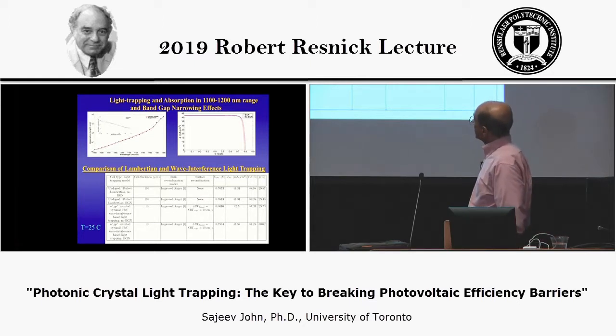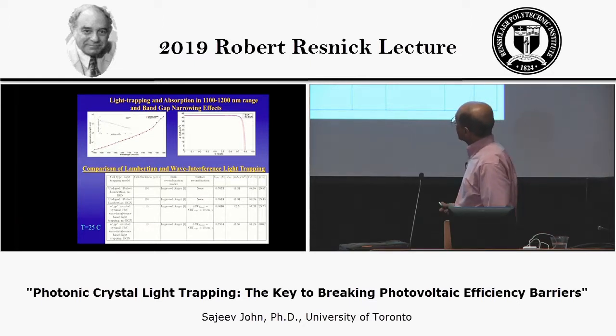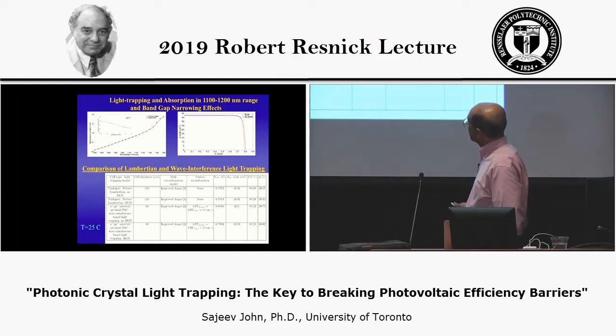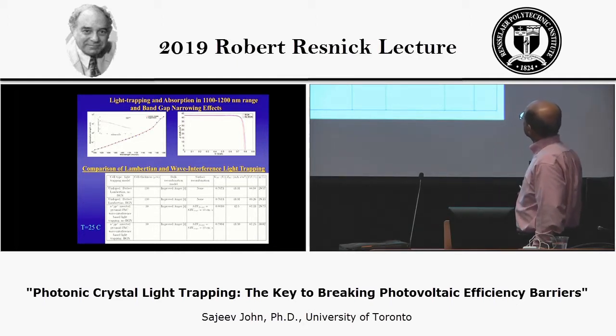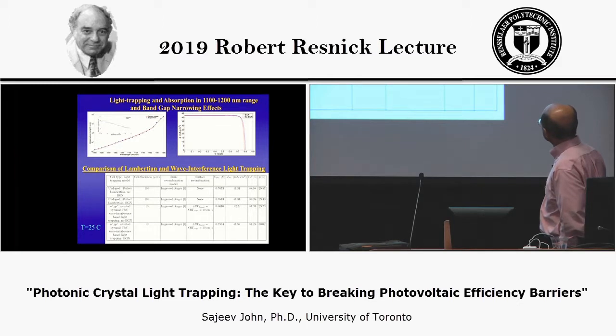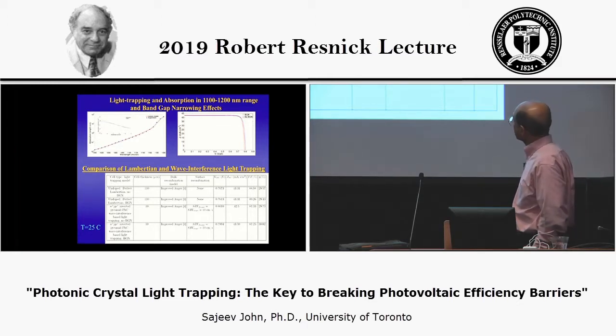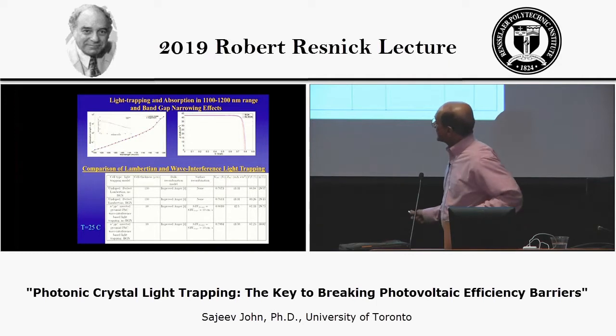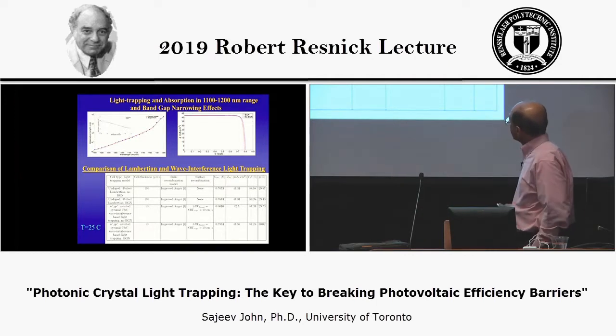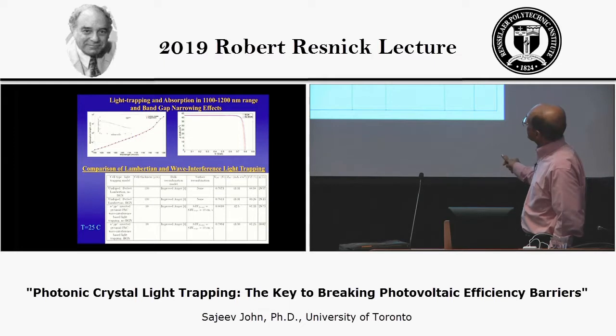So here's some comparisons of these hypothetical Lambertian cells with 110 microns, with and without this band gap narrowing. The photocurrent density doesn't improve at all, but the voltage goes down a little bit, and so the efficiency drops slightly below the original efficiency of 29.5%. If we do this for our inverted pyramid cell, we gain another milliamp or so from this very long